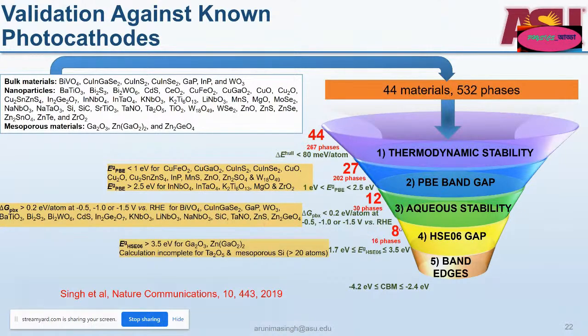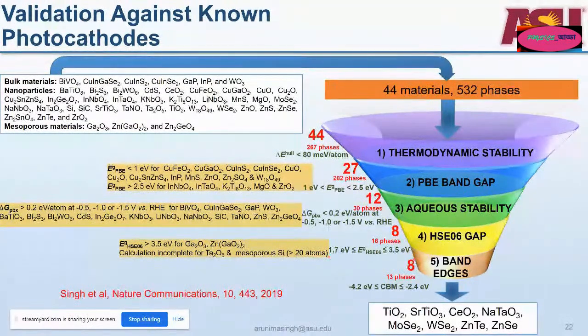And then when we look at the band gaps with a more accurate functional, there's about 8 which remain. And for some of the oxides, we get a band gap much higher than 3.5 eV. For certain other materials, we were not able to do the calculations because these calculations are fairly expensive and did not complete in the wall time of the supercomputing resources. And then we look at the band edges and we find all of these 8 materials had suitable band edges for CO2 reduction, and what emerges out of this screening is fascinating.